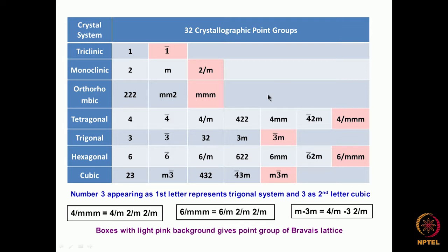If we look at a tetragonal crystal, the 4-fold rotation contains 4-fold rotation, 2-fold rotation and 1-fold rotation. These are all the symmetry elements present. When we try to represent it, if only rotation is available, the maximum rotation is what is used to represent it. Similarly, if it contains a combination of rotation and a mirror, then we may have 4mm, if we take it.